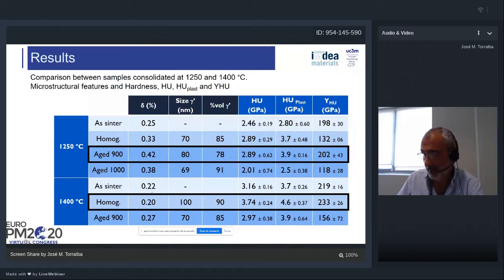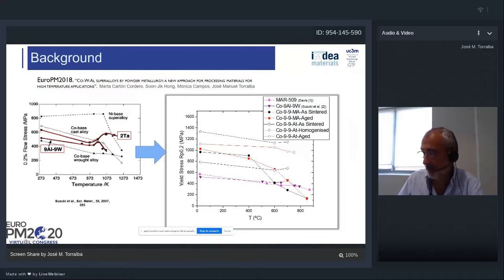If we come back to this figure that we proposed at the beginning of my talk, in which we have, in a previous work, the behavior at high temperature, we can check how those materials with higher misfit, which was the homogenized and the aged material, have much higher values for the yield stress at high temperature than the material sintered or other materials from other different consolidation methods.